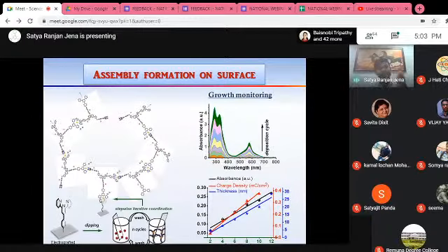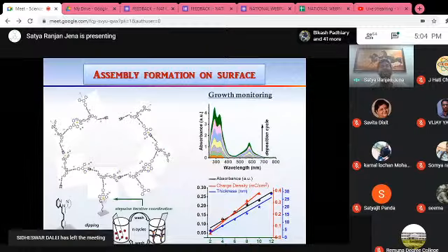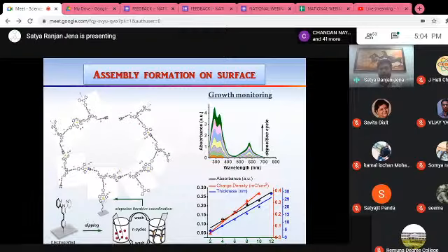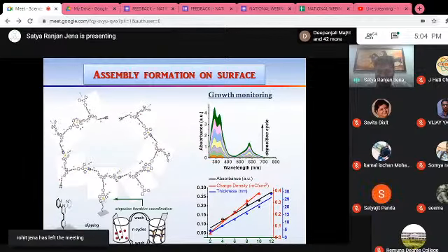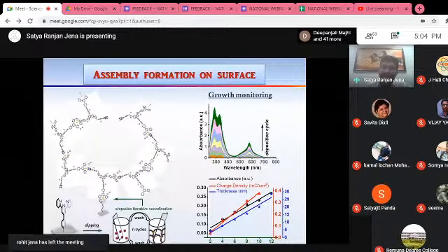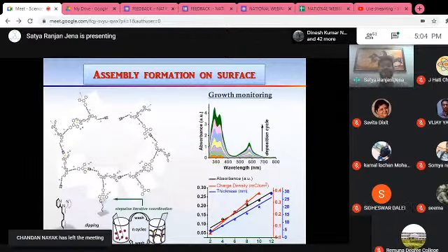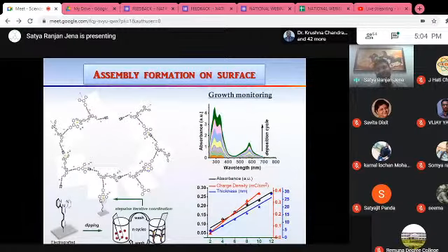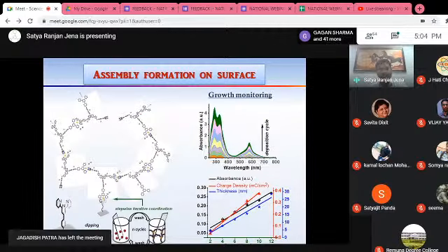This was further characterized by different techniques, through charge density, because if you have more iron terpyridine moiety, you have more redox active centers. So you will get more charge when it grows continuously. You see the red one is the charge density from different deposition cycles. It is growing linearly. Similarly, absorbance is also going linearly. And through ellipsometry, we checked whether the thickness is also increasing or not. You can see the blue one, which is also growing linearly. In this way, we monitored the growth.